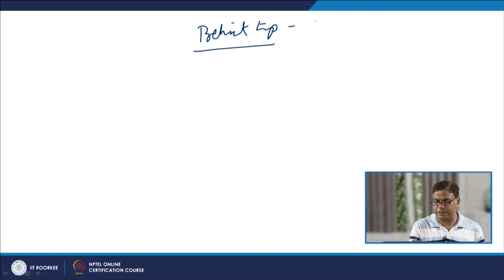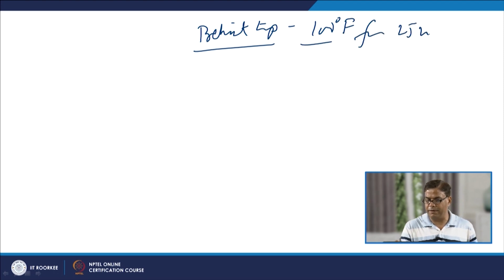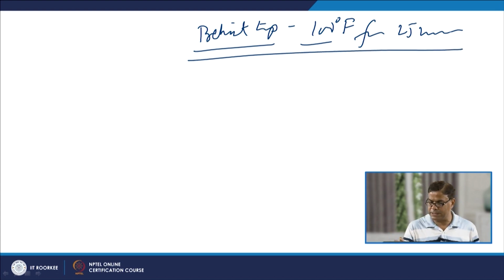So, we have to fix up at least one thing, like preheat temperature is fixed, say 100 Fahrenheit for a 25 thick plate. Then for this preheat and for this thickness of the plate of a given steel, say A514 B grade steel, then we need to establish the heat input for the process which is being selected. And heat input, how can we choose?